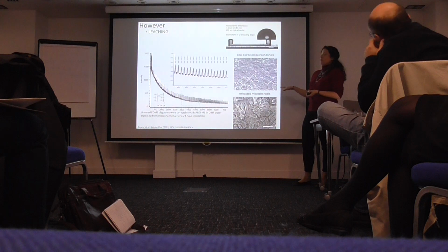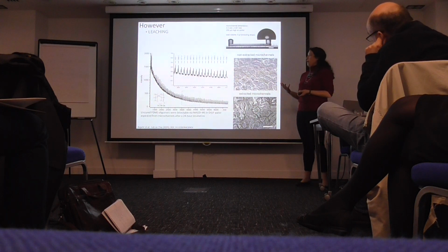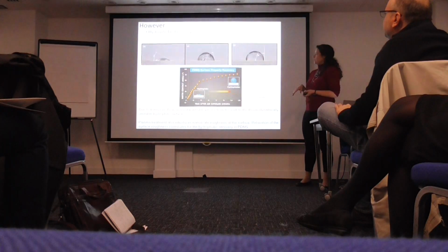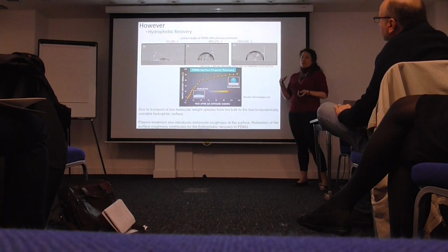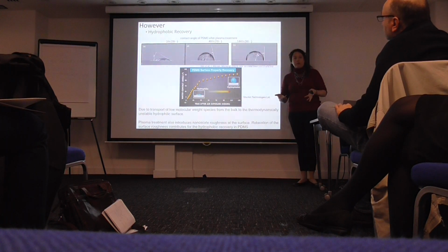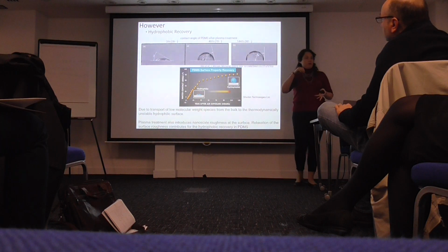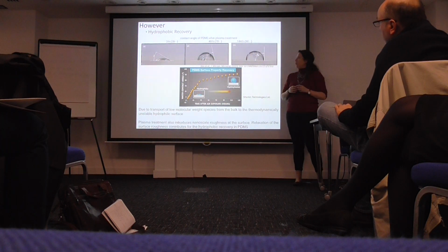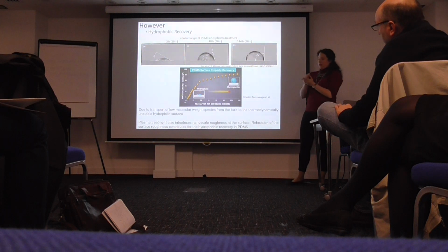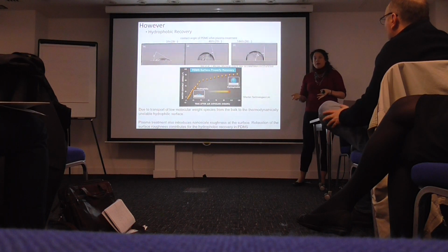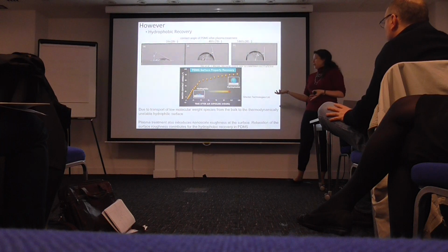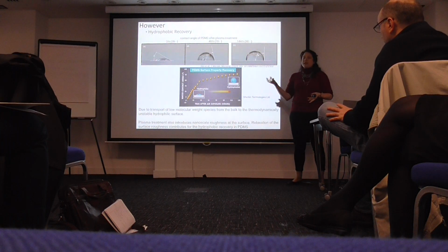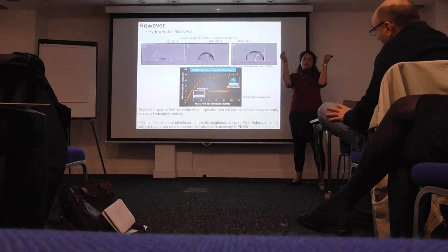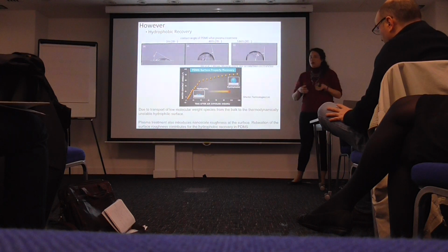Now, this phenomenon, we might know it most by the reversibility of the surface, the hydrophobic recovery of PDMS. PDMS comes out as hydrophobic. If you put a drop on it when it's first made, it makes a really nice bubble. You put it into plasma, then it gets hydrophilic, but it takes 3 days to recover and become hydrophobic again. Actually, we don't know exactly what's happening inside of the PDMS. We do think it's because of the monomers making it to the surface. So as a result, it gets back to hydrophobic.